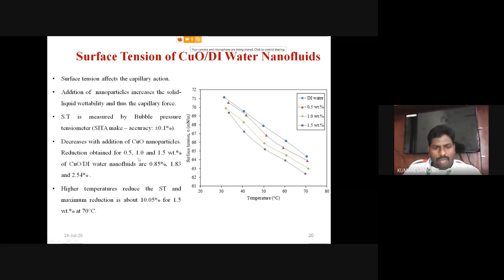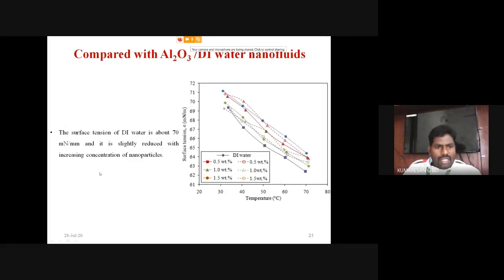That reduction obtained for 0.5, 1.0 and 1.5 wt.% of CuO DI water nanofluids are 0.85%, 1.83 and 2.54%. Then high temperature reduces the surface tension value and a maximum reduction of 10.05% is attained for 1.5 wt.% at 70 degrees Celsius. Then this copper oxide performance is compared with the aluminum nanofluid. The surface tension of DI water is about 70 millinewton per meter, and it is slightly reduced with increasing the concentration of nanoparticles. That means there is no impact on the surface tension by adding very low mass concentration of nanoparticles in it.